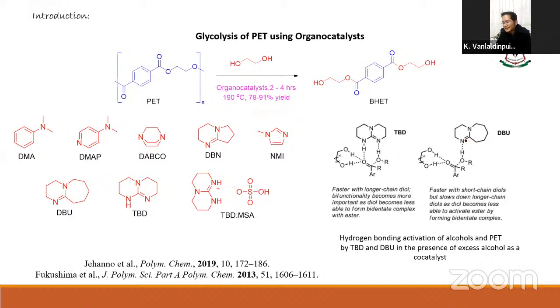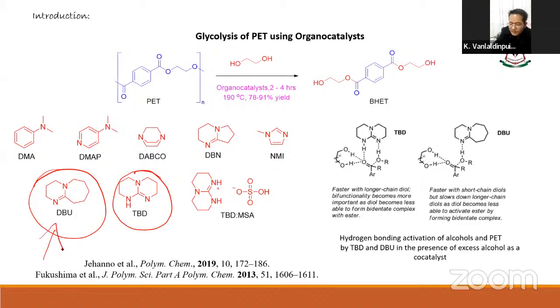And recently, organocatalysis was also explored, and it was investigated for that same transformation, the glycolysis of PET, and they are quite effective, giving up to 91% yield. So this process, that means glycolysis of PET using organocatalyst, becomes more efficient when strong bases are used. For example, DBU and TBD. Okay. And among these two, DBU is more basic compared with TBD. But TBD shows more efficacy. It is a better catalyst when it comes to the depolymerization of PET.